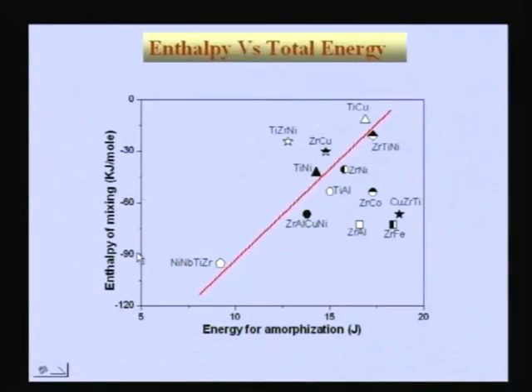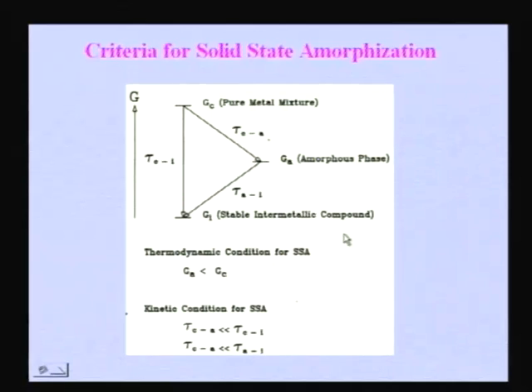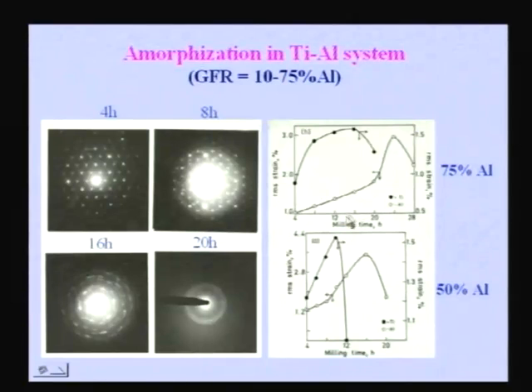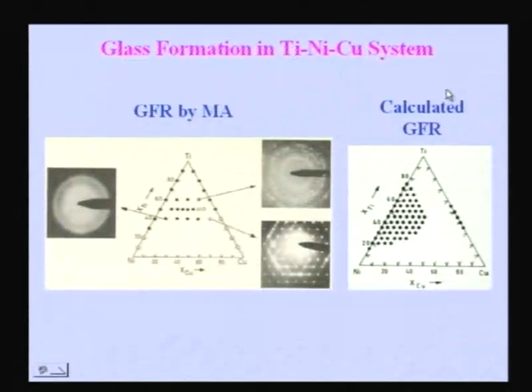And one can correlate the energy required for amorphization to thermodynamics and show that this is for amorphization. One can do a similar thing for any phase formation. There is always a direct correlation between thermodynamics and the energy required for any phase formation. So one can have strong correlations, and this is one thing which we have talked about at some point of time. What are the criteria for amorphization? One, thermodynamic criteria, kinetic criteria, and we have also talked about the critical strain that is required for amorphization to occur, and we have talked about the calculated glass forming ranges from thermodynamics, which can be compared with the experimental glass forming ranges.